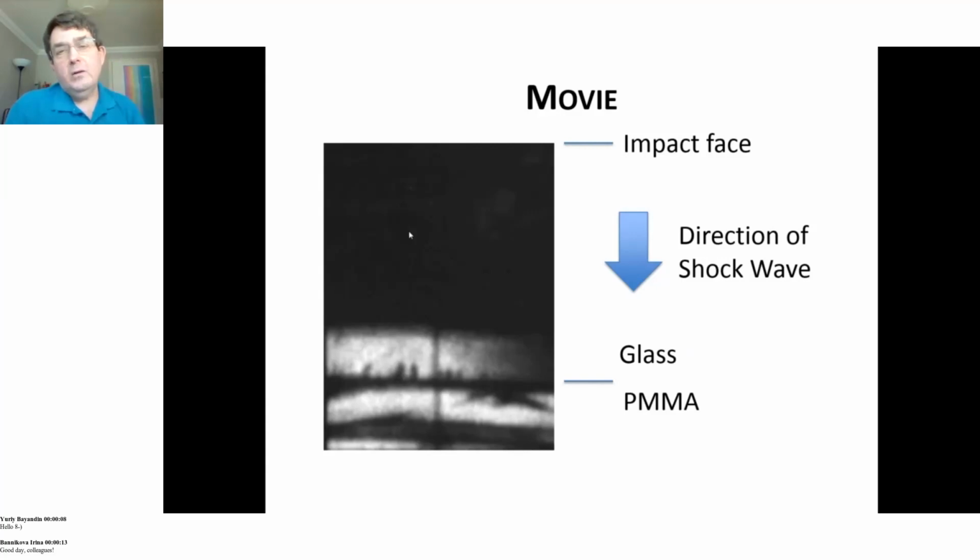So this is where Oleg and his group have looked at these kinds of phenomena, where you get a number of radiators interacting with one another in a bulk process where the population includes nucleation and growth of these multiple microcracks affecting the material property. Basically, the glass turns into a powder, and a powder that has a permanent densification associated with it. So an interesting, and if you're doing armor ballistics, important process.